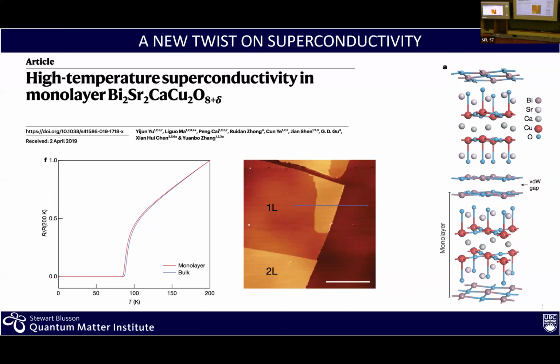The next breakthrough that brings us back to cuprates is the following. So we're seeing graphene. I think you're familiar with graphite. It exfoliates very easily. That's why you can use a pen and write on paper, because you leave behind parts of graphite. But if you look at cuprates, and here is one particular system, the bismuth strontium calcium copper oxide, the key element are these copper oxygen planes here. It's a nice square copper oxygen plane, CuO2. So one copper atom and 4 oxygens around. And those two planes is where superconductivity takes place.